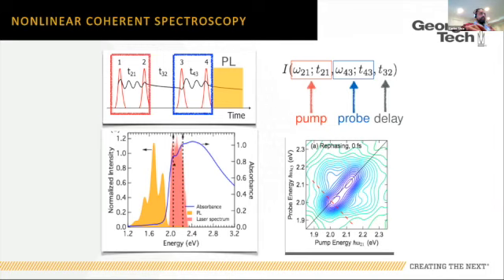So here the idea, that's not what I'm going to talk about, but if I tune my laser to, for example, overlap the 0,0 and 0,1 transitions and measure the time-integrated photoluminescence, I have one energy axis defined by a pair of pulses, and another energy variable defined by the other pair of pulses through the delays. These are coherent delays, and then something like a pump-probe delay, the population time. So I can measure population dynamics, but importantly, I can measure a two-dimensional spectrum that allows me to look at spectral correlations, and that's what I'm going to be looking at today.